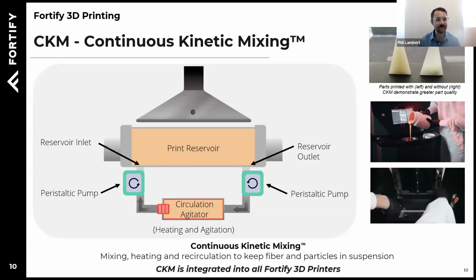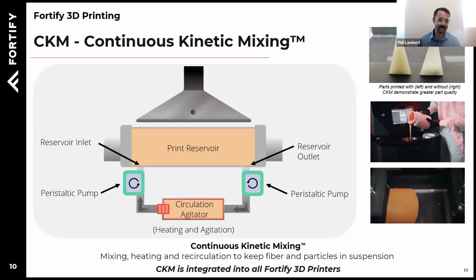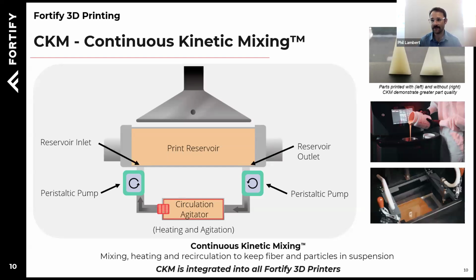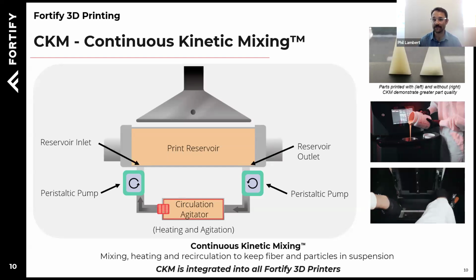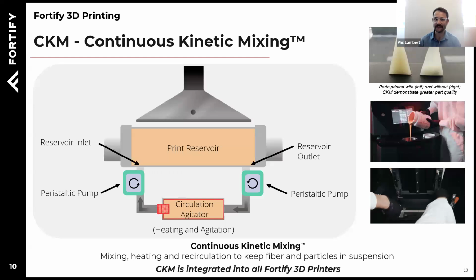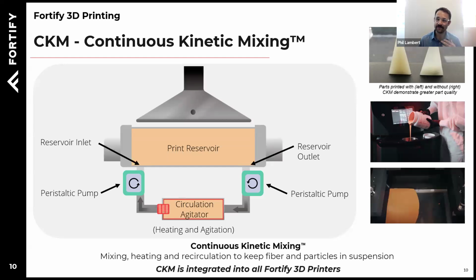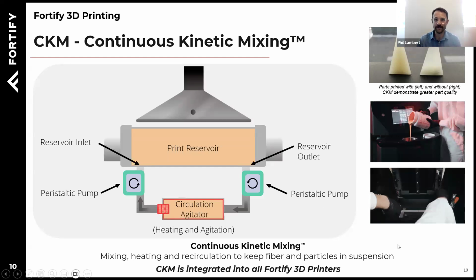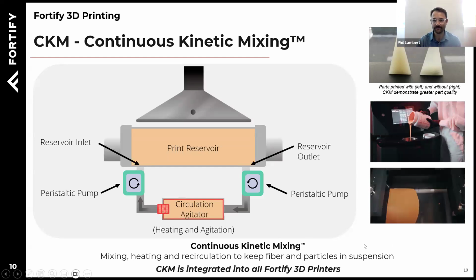And we do that in part due to a technology on our machine called continuous kinetic mixing. So continuous kinetic mixing is a module that continuously pumps, using peristaltic pumping, our resin through our reservoir through a circulation agitator, where the material goes to get mixed and heated and then redistributed back into our print reservoir. And so this material is constantly moving, constantly getting heated if that specific type of resin requires heating, so that we are constantly making sure that our resin is homogeneous from the start of our print to the end of our print. And this technology is essential for many of our resins to be processed and to maintain the final part properties that you need for your application.